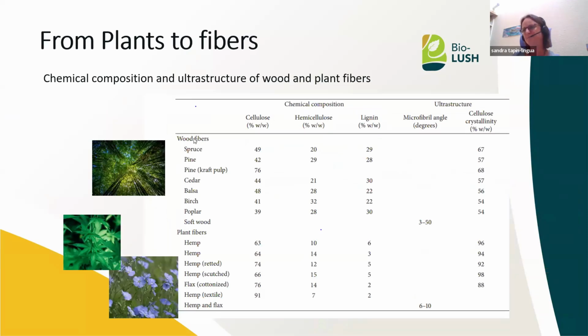If we focus on the composition and the structure of the fibers, we can have really different compositions. From wood, we have different qualities of wood. First, softwood like spruce, pine, cedar, for example. Others are hardwood like birch and poplar, which is the most used to make pulp. We have different qualities in terms of chemical composition: cellulose, hemicellulose, and lignin. Cellulose is always at a higher content, and lignin, present in a lower quantity, is the second component present in this type of fibers. Depending on the quantity of lignin and the nature of the lignin, fibers will be more or less well individualized by mechanical or chemical treatment.